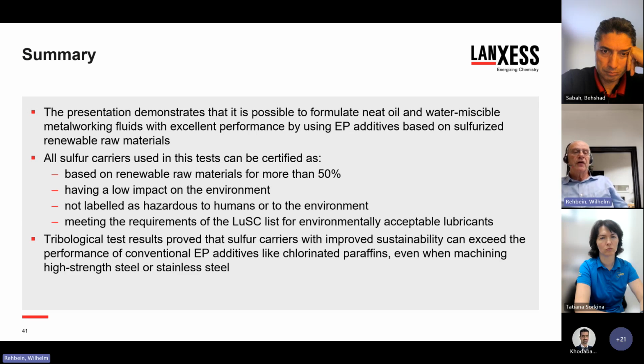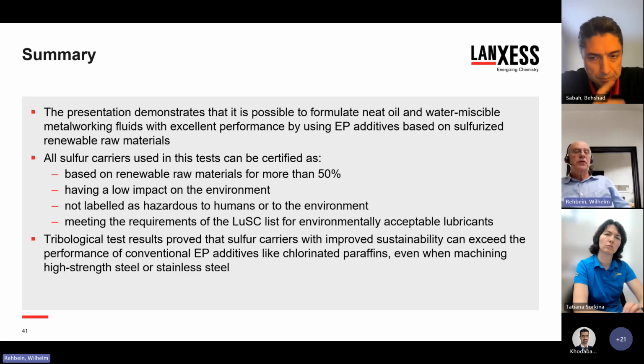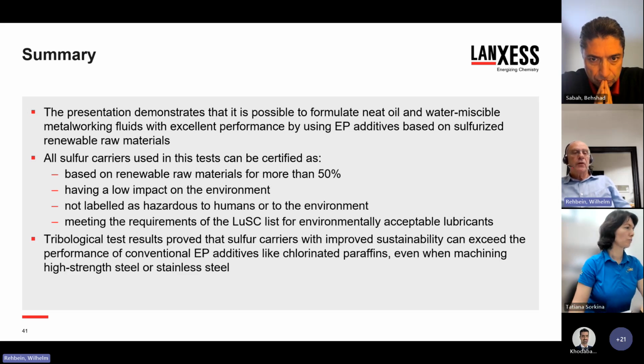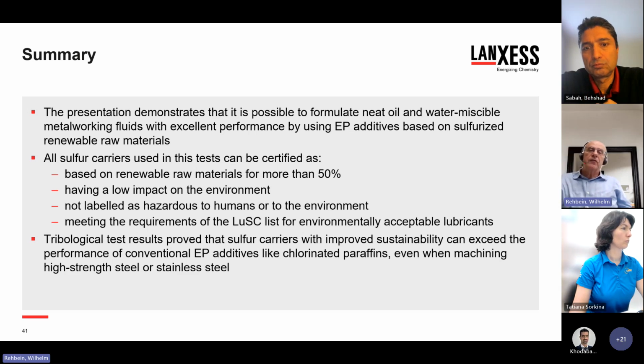They are not labeled as hazardous to humans or to the environment, and they actually meet the requirements of the so-called LUSC list for environmentally acceptable lubricants. I think the tribological test results show that sulfur carriers with improved sustainability can even exceed the performance of conventional EP additives like chlorinated paraffins, even when machining high-strength steel or stainless steels.